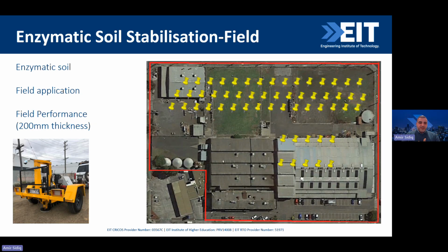Then we did some of these field tests. So initially we stabilized the site at the first 200 millimeter thickness by using the enzyme and cement, and we did these falling weight deflectometer tests at different spots. So they are about 10 meters away as a grid, and then we did some of the tests in this condition as well to understand what actually the behavior is.